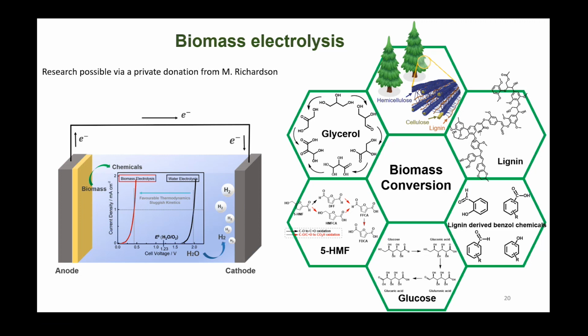If you do that, instead of the oxygen evolution reaction at the anode, we could convert this biomass to high value chemicals, because we would just partially oxidize it. And when we do this, we would get protons that will be converted at the cathode, where you would still have hydrogen evolution and formation of hydrogen. There are advantages of doing this, in particular that these oxidations happen at lower potentials compared to oxidizing water. That's one advantage that would overall lower the cost of hydrogen coming from these processes, but also, and our techno-economic assessment showed that this is actually the biggest value, you could have greener manufacturing processes for commodity chemicals, should you control the selectivity well enough.